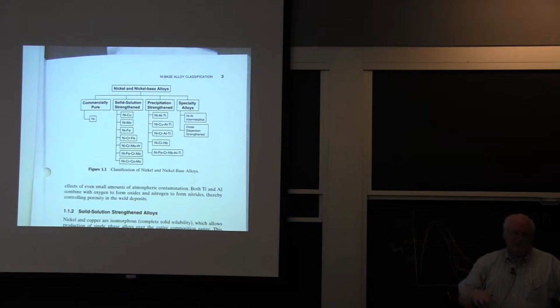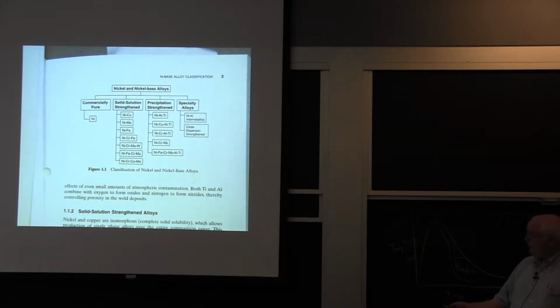I mean, the old stuff was like 300. So it was 50% harder, first try. Well, it was only because I knew that nickel aluminum and nickel titanium, or in this case nickel aluminum, had a very strong affinity for each other. Both of them dissolved in nickel copper alloys at a limited concentration. So if you heated them up at high temperatures, they should go into solution. At lower temperatures, they should join up and bond to each other in this nickel 3 aluminum. And they did, and we got high hardness and we got precipitation hardening.